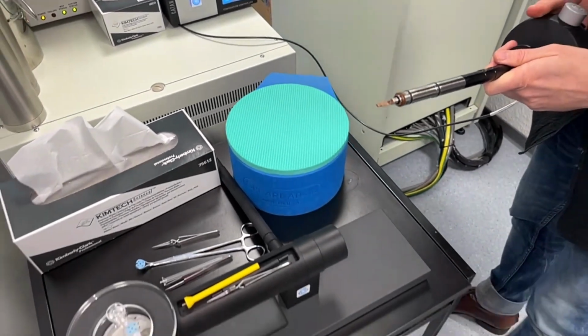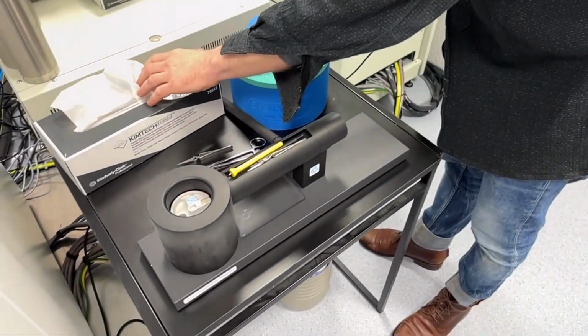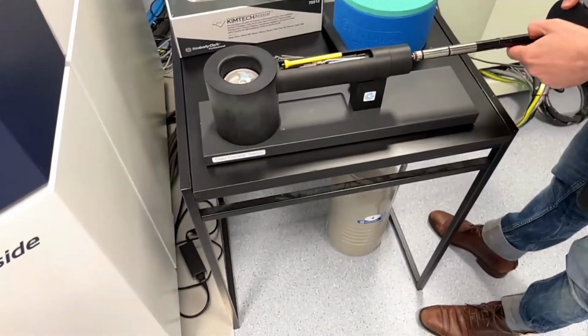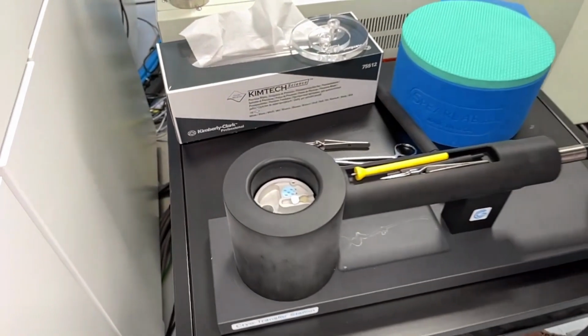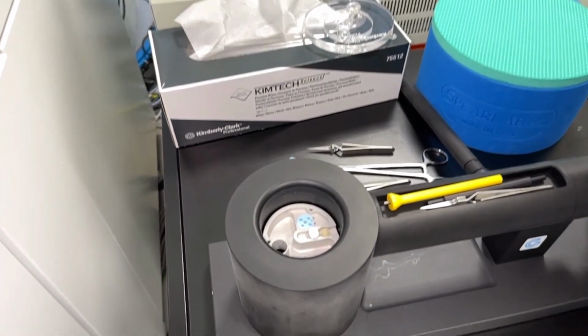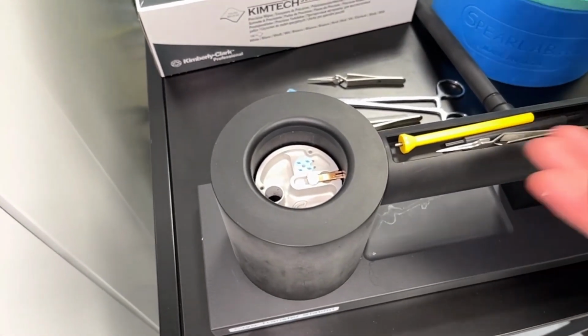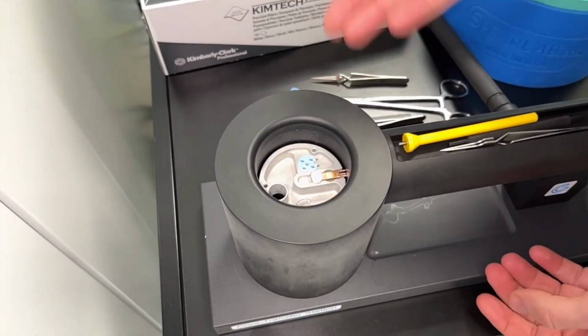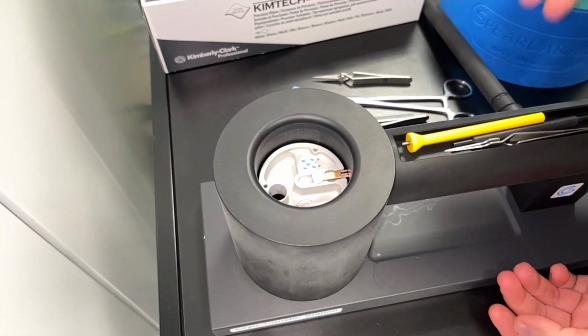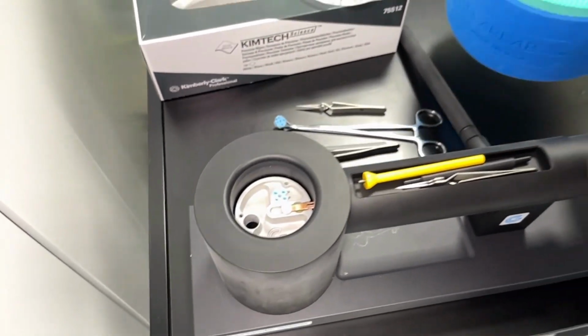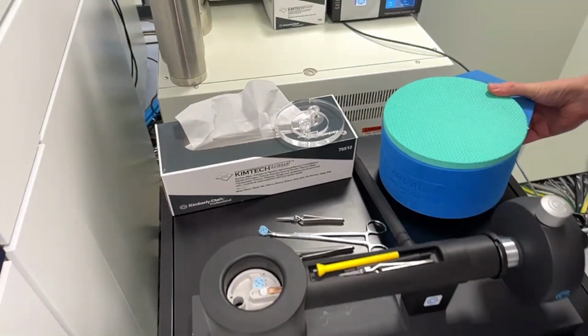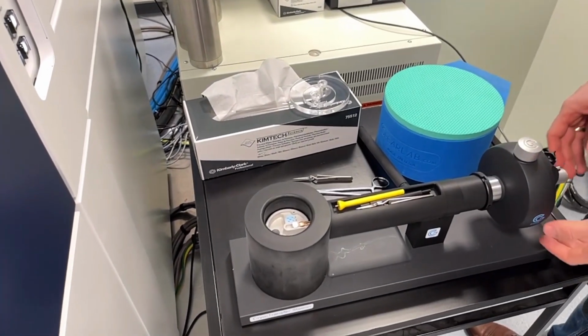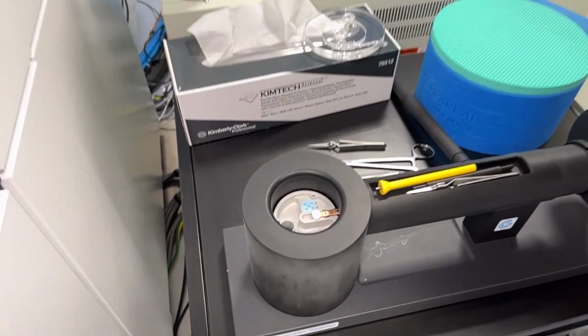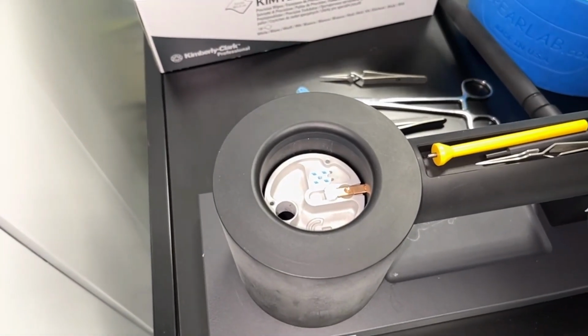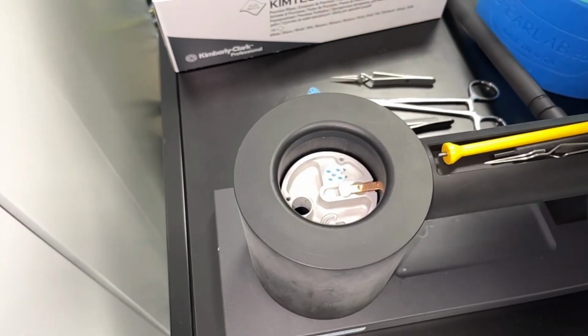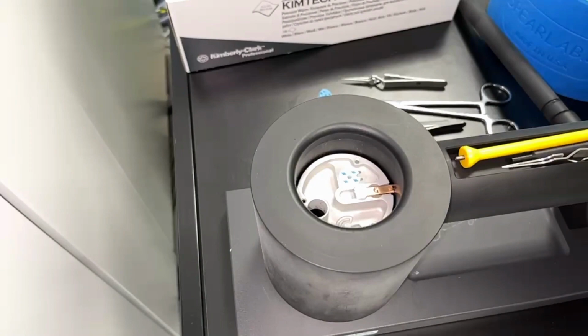What you see here is called the transfer station. This is where you would usually have liquid nitrogen in this dewar here at the top. And if you want to put a sample into this holder, what you would do is to have a sample that has already been frozen by just dipping it into liquid nitrogen. You can do that here or in an external foam dewar like this. Or there are different methods. You can also plunge freeze it in liquid ethane, especially if you have biological samples. And then in this station, under protected liquid nitrogen atmosphere, either liquid or under a vapor, you insert the sample in here, close the shutter, and then transfer it.